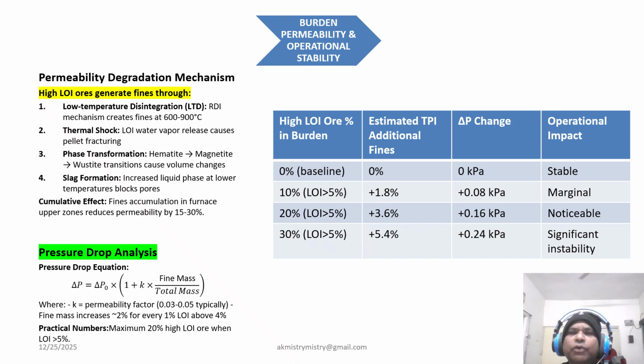Let's start with how high LOI ore silently degrades blast furnace permeability. Four mechanisms are at play: low temperature disintegration, thermal shock from water vapor, phase changes, and premature slag formation, which we have already discussed in the earlier presentation. Together, they generate fines that reduce permeability by up to 30%, as shown in the slide.